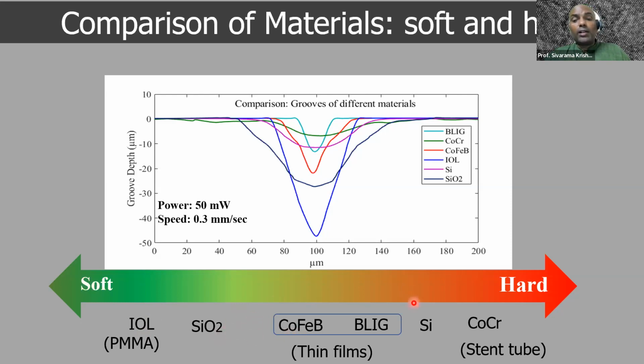Apart from common silica, we also looked at films, cobalt, iron boron, and BLIG, which is a very important material for magnonics along with YIG. So under similar conditions, we essentially figured out the nature, the shape, and the width of grooves which can be written across this spectrum of materials.